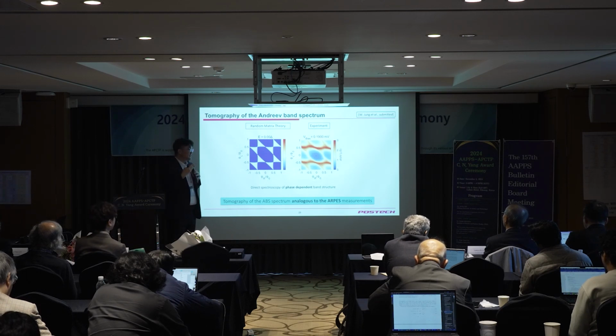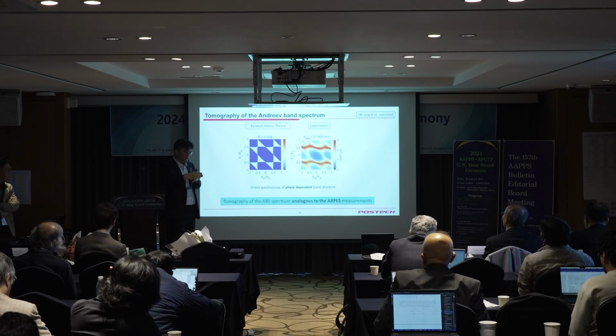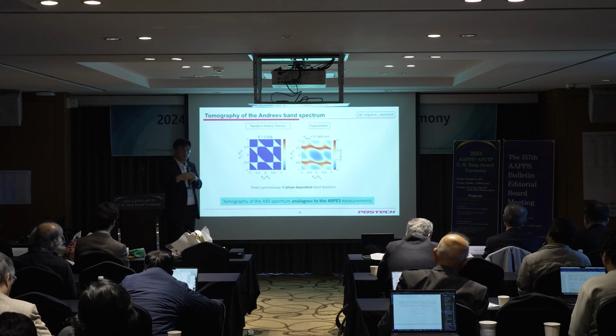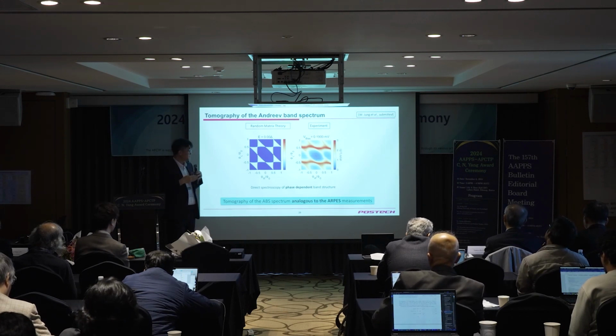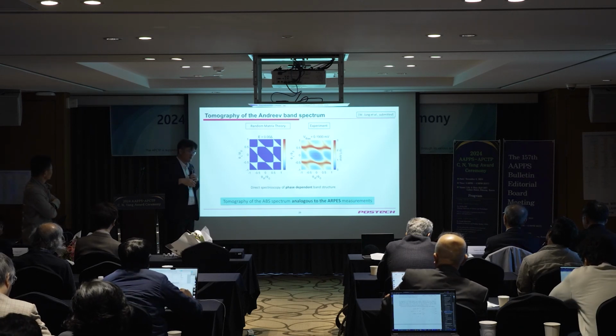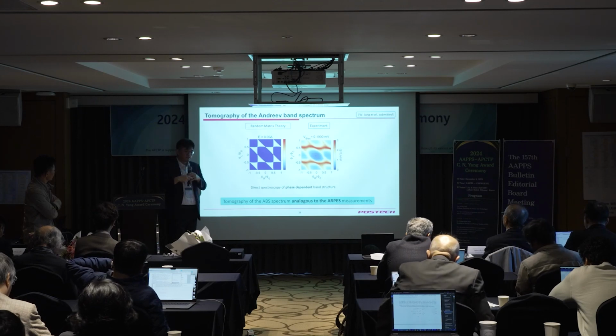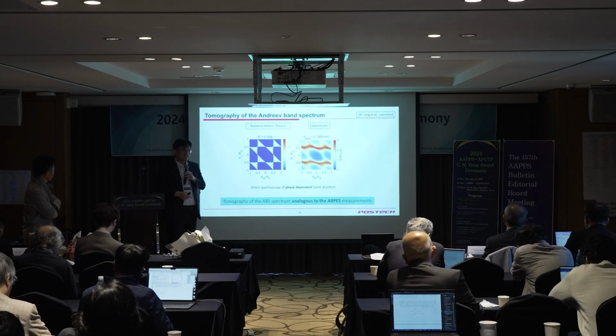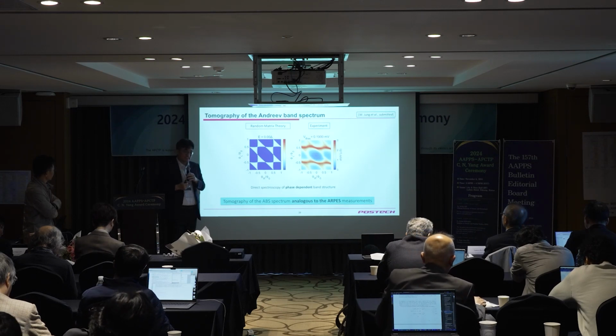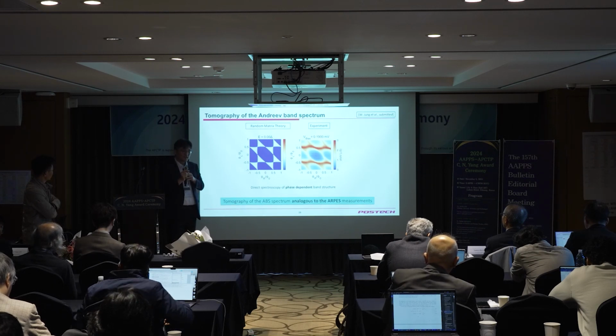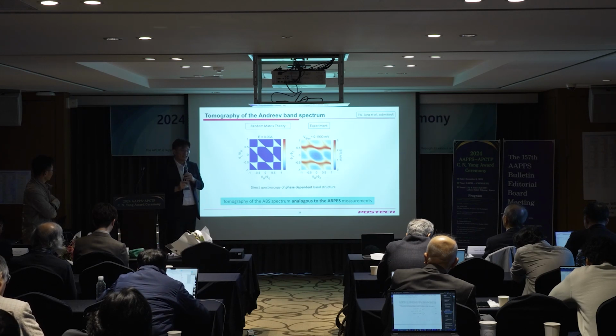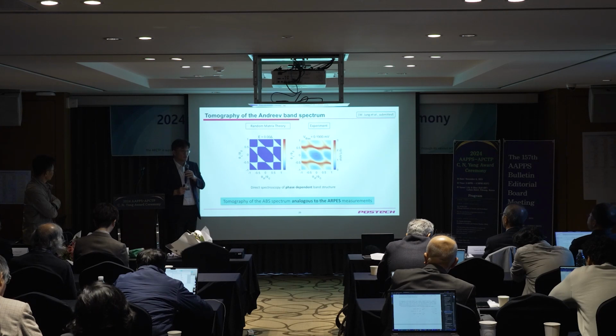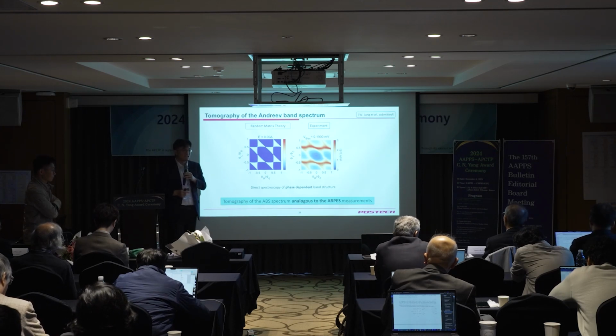And we think that because there are so many different conducting channels, which all have different superconducting contact transparency gamma, it is effectively well described by the random matrix theory. So we virtually scan all possible parameter space because we have too many conducting channels. To give a neater result, we had better move to a smaller size of graphene so that we deal with only a few conducting channels, hopefully one channel, and maybe we can use it as an Andreev level qubit as well. That is one direction we can think about.